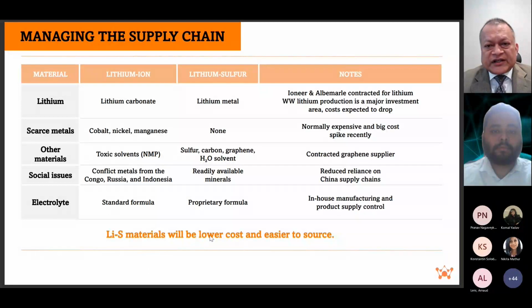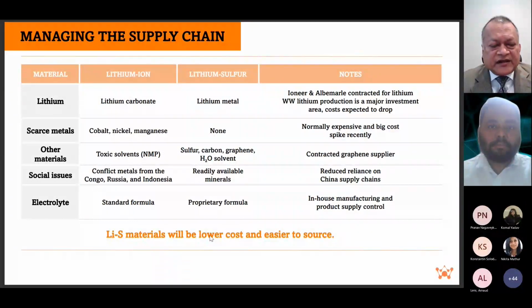Managing the supply chain, traditional lithium-ion versus lithium sulfur. We need lithium metal foil. Depending on how you address the chemistry, as I was mentioning, if you can deploy organic sulfur active material instead of mechanical mixing of sulfur and graphene, and then tie down sulfur better than where we are today, you would be able to reduce lithium metal consumption. We do not use any heavy metals. So the battery in general, the chemistry in general is a lot more sustainable and environmentally friendly.